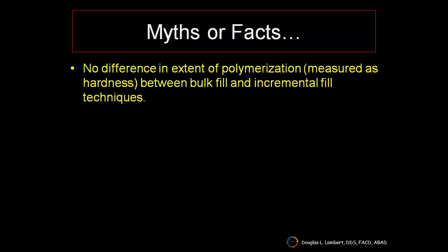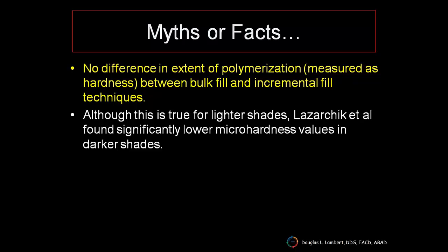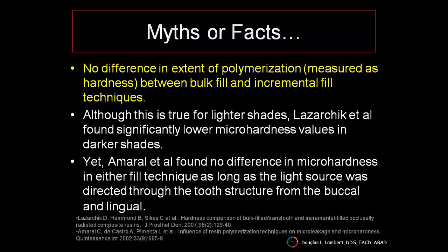And this one. There is no difference in the extent of polymerization when measured as hardness between bulk fill and incremental fill techniques. Now, this has been shown to be true for lighter shades, and one study found significantly lower micro-hardness values in darker shades. However, this particular study found no difference in micro-hardness in either fill technique, whether it was bulk or incremental fill, as long as the light source was directed through the tooth structure from the buccal and the lingual. Let's think about that for a minute and hold on to that thought. We're going to circle back and look at what happens when we direct the light source from the buccal and the lingual through the tooth structure in a couple of minutes.